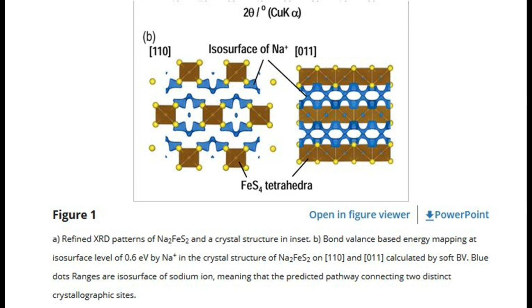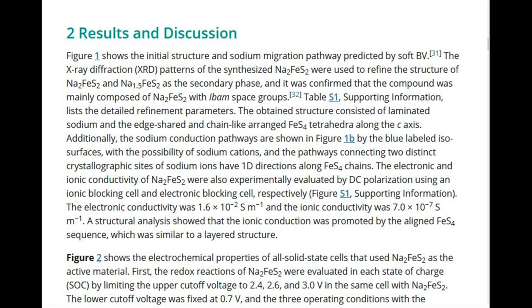Figure 1. A. Refined XRD patterns of Na2FeS2 and a crystal structure in the inset. B. Bond valence-based energy mapping at isosurface level of 0.6 eV by Na+ in the crystal structure of Na2FeS2 on (110) and (011) calculated by softBV. Blue dots ranges are isosurface of sodium ion, meaning the predicted pathway connecting two distinct crystallographic sites. 2 Results and discussion.